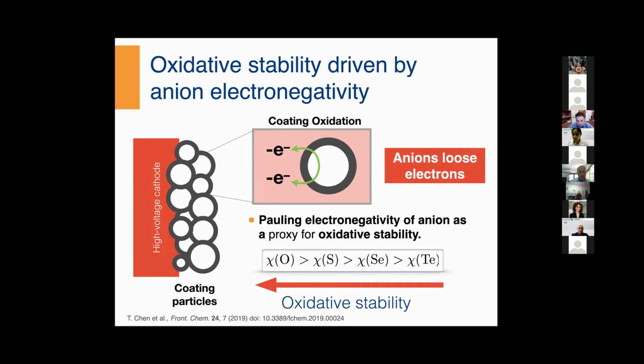This is not surprising, right? If you have an electron tightly bound to a specific species like oxygen, it's much harder to extract this electron or effectively oxidize the coating or the electrolyte by this mechanism, right? So moving down the group of a specific category, chalcogenides, halides, and so on, halogens, sorry, the anodic stability window is bound to decrease.